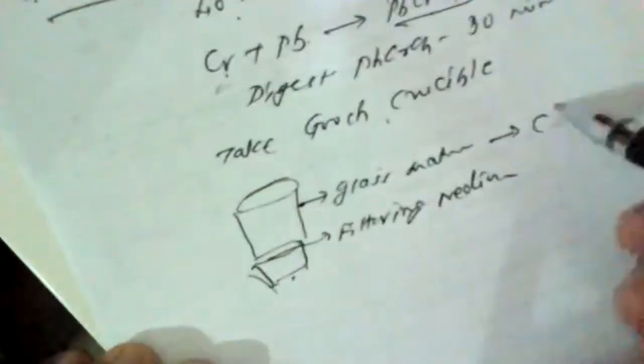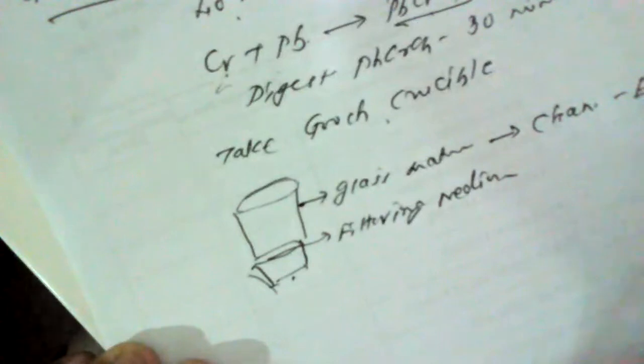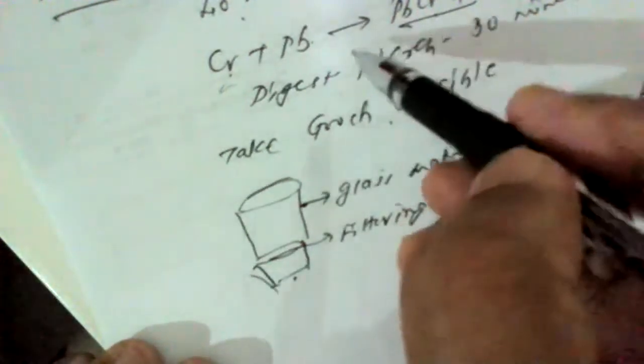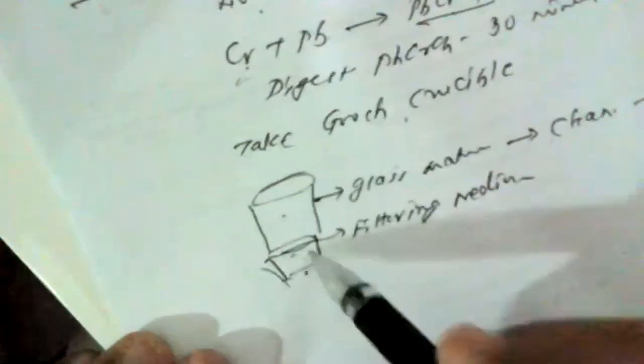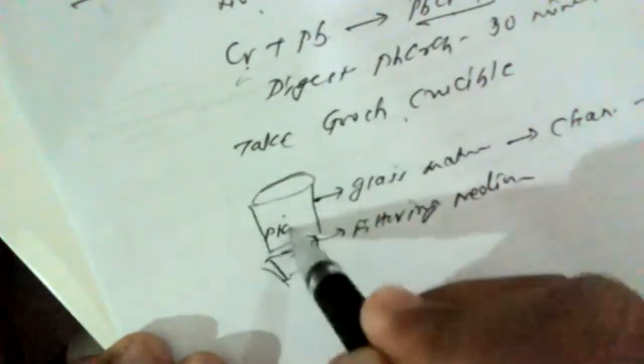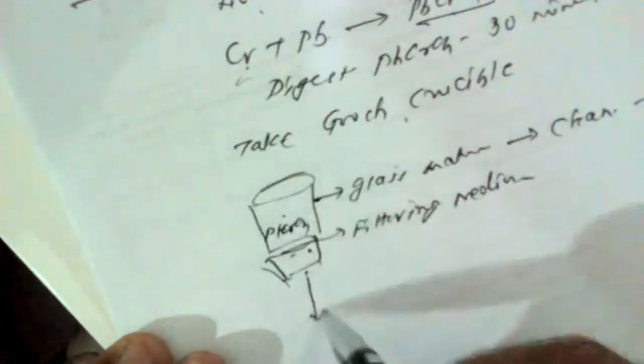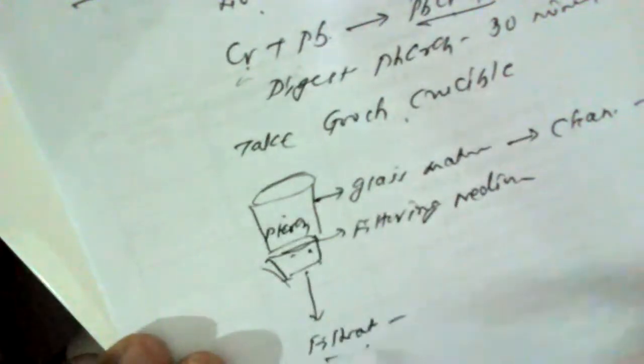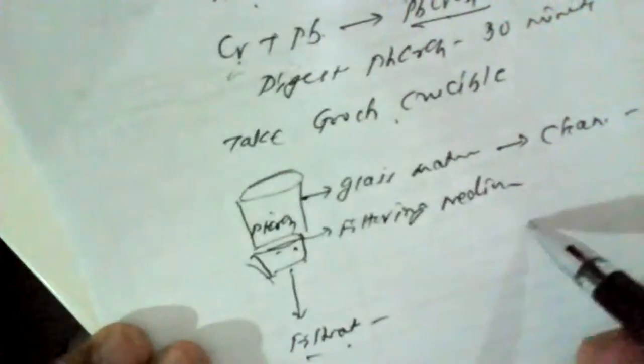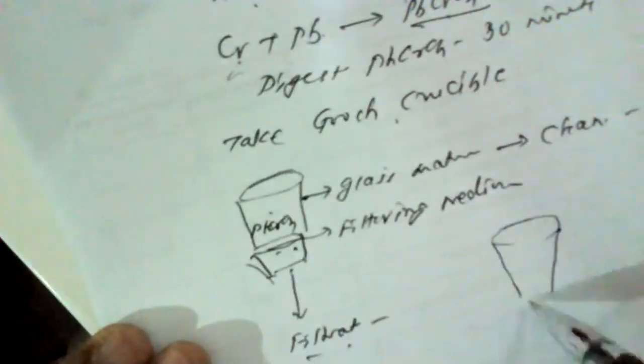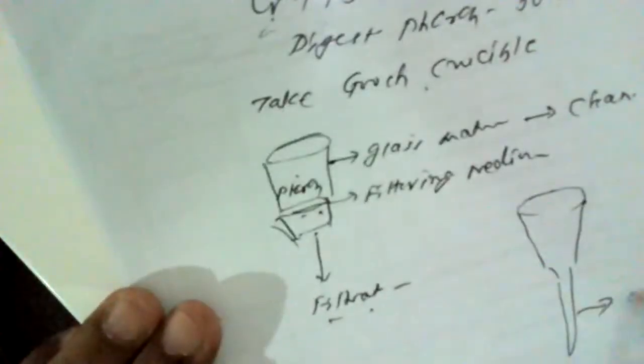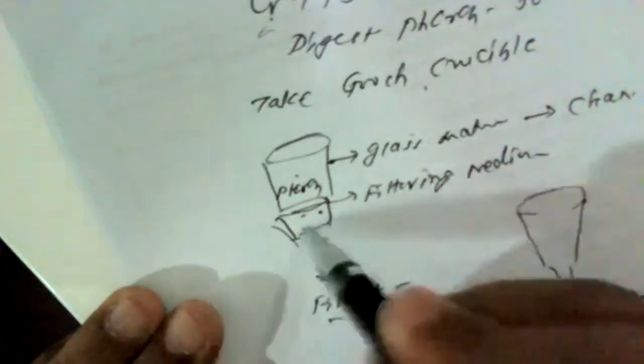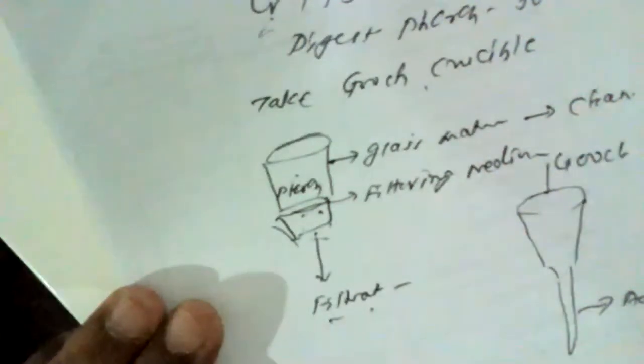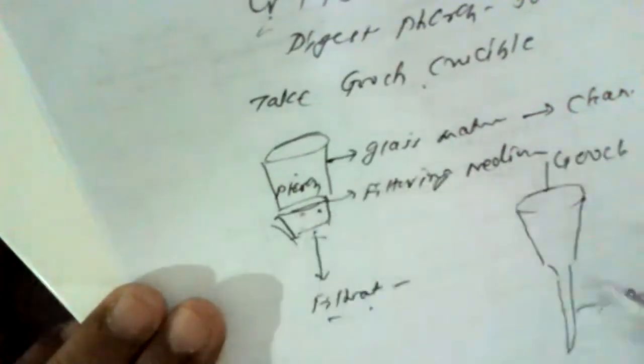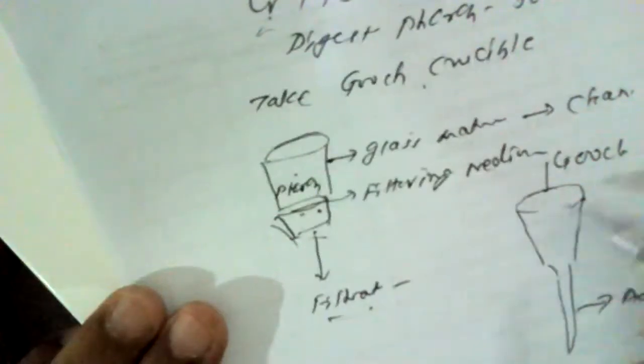First of all, we have to clean this Gooch crucible and take the weight of the empty crucible. When we add the digested solution in this Gooch crucible, this filtering medium preferentially retains the precipitate of lead chromate, PbCrO4, and here we obtain the filtrate or the mother liquor. This Gooch crucible is to be mounted on a specially designed adapter, and by using a suction pump, the solution can be easily filtered.